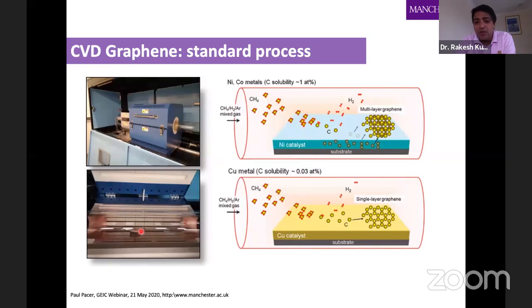So mostly nickel substrate is used for multi-layer graphene, because the carbon atoms are soluble in nickel and they start nucleating within the nickel substrate, within the metal. On the other hand, if you want to grow graphene on copper, the carbon atoms in copper are insoluble, so it nucleates on top of the copper. But you can still make two layers or three layers